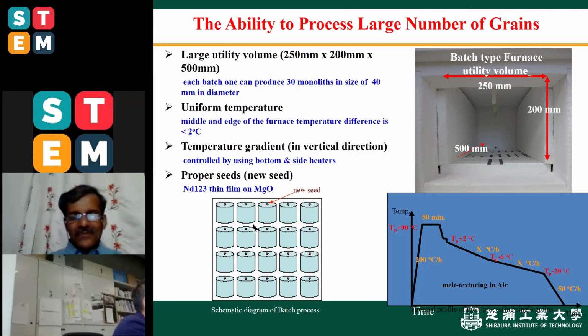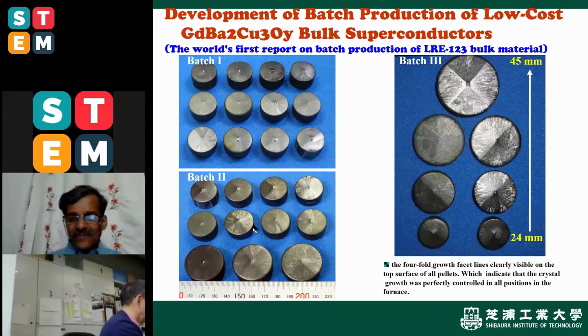To succeed in such a story, a novel thin film of neodymium 123 seed grown on MgO crystals was used, and we adapted a 2-step heat processing. Then finally, we found a very good first report on LRE 123 batch production. This was highlighted in Superconductor Science and Technology. In such a result, you can see batch 1, batch 2, batch 3, even from 24 mm to 45 mm batch production samples were done.